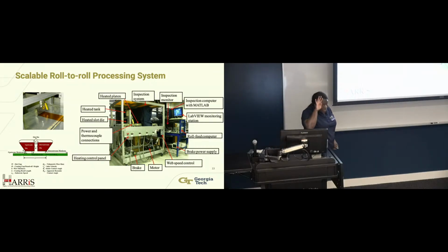This is an image of the setup that's in GTMI, our lab scale roll-to-roll system. This is about 2 meters this direction, 1 foot into the depth. And then the thickness doesn't really matter because the thickness is going to be based on what you coat and deposit on top. The slot die sits here, and this one is the 4-inch die that actually went around the room, and it can create these nice structures here, as you can see. And I believe that's blackstrap molasses. So when people ask, what can we process? We say anything. We'll try to process water if you give it to us.